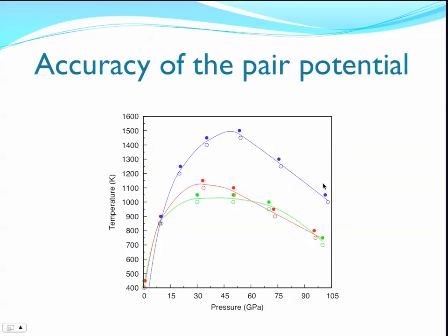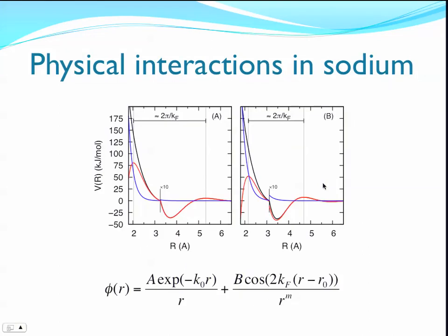So another important result is that now we try to understand which part of this analytic potential is responsible for anomalous melting. Okay, actually, maybe I should describe the form of this potential in a bit more detail. So the first part, the first term, is this so-called screened Coulomb interaction, a purely repulsive wall of the potential, and the second term is this oscillatory potential that induces this long-range waves in the potential.